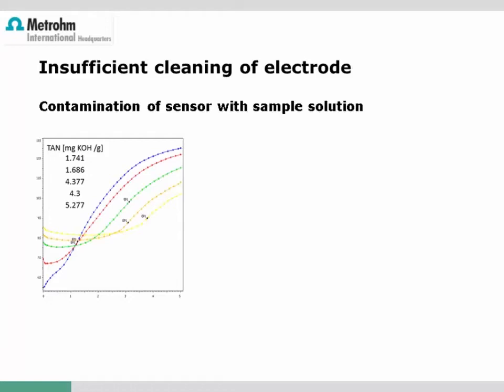Again, a comparison of several titrations in a curve overlay may help, like this example from a non-aqueous titration of the acid number of used engine oil. These samples are very sticky, contaminated with black carbon or other solid particles. You see a real pain for any pH glass electrode. The increasing contamination of the electrode can immediately be detected when looking at the curve overlay of several samples with the same sample size. Each single curve still looks more or less reasonable, but first of all the equivalence points are shifted to higher values, and a much better sign for insufficient cleaning, the start potential of the titrations is varying significantly. Since always the same sample size is used, this should definitely not be the case.